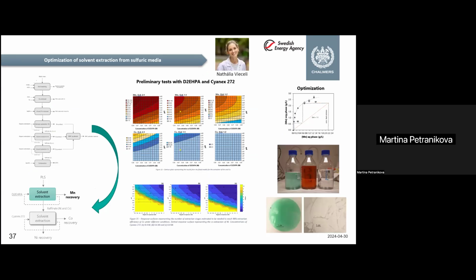We have also been focusing a lot on the optimization of solvent extraction, and we did a lot of research on manganese. Previously, we could see that a lot of recycling is done by its precipitation because it doesn't have any value. But now there is an increased interest from the industry to also recover manganese with solvent extraction, because it got onto the list of critical raw materials, and it's also needed for the production of NMC materials. With this method, we can achieve very high purity. We optimized and developed the process where we achieved very high purities for the manganese recovered from the batteries.